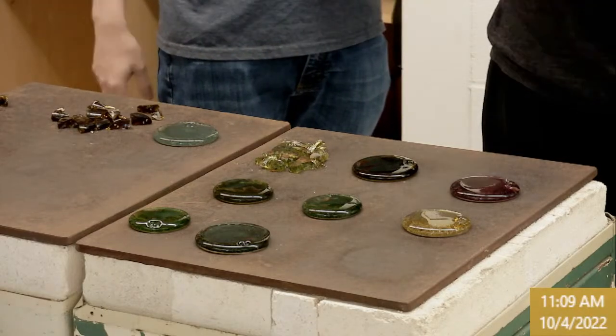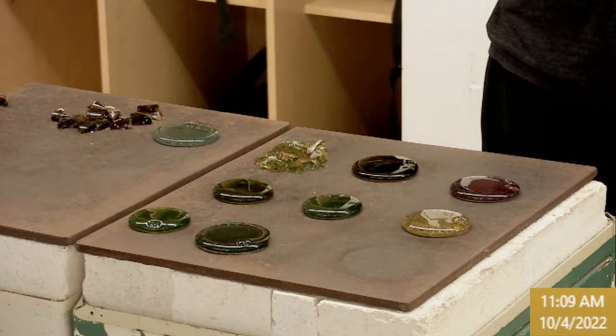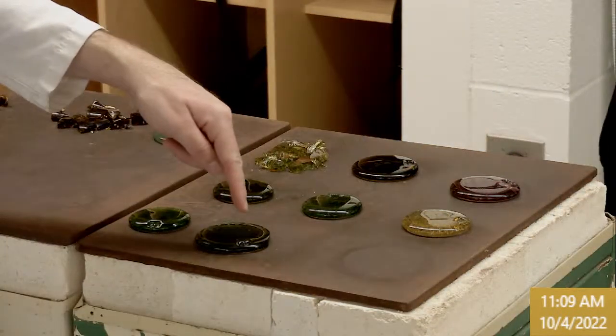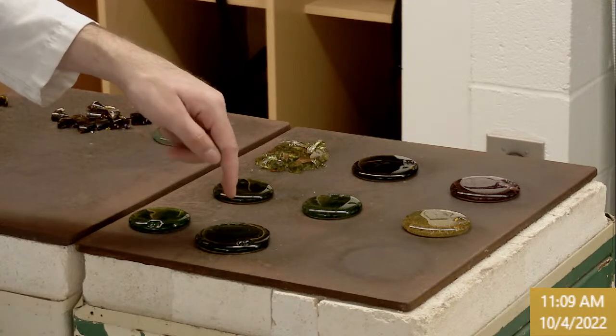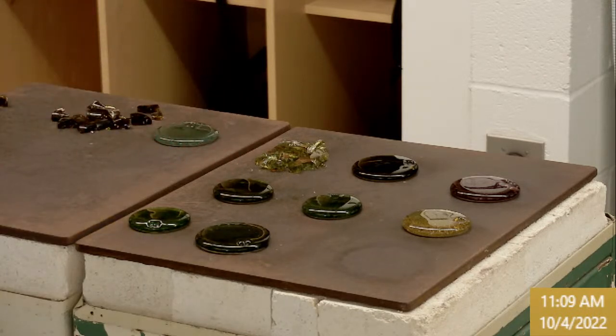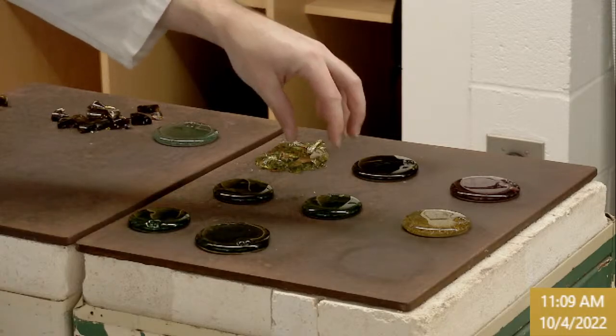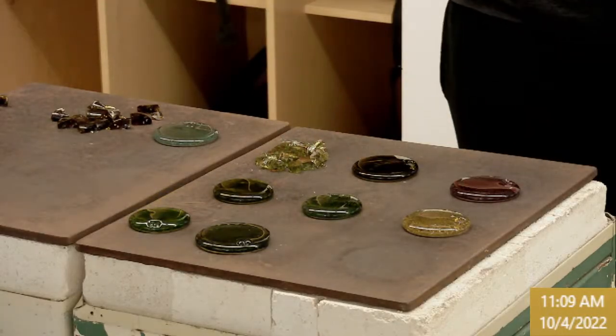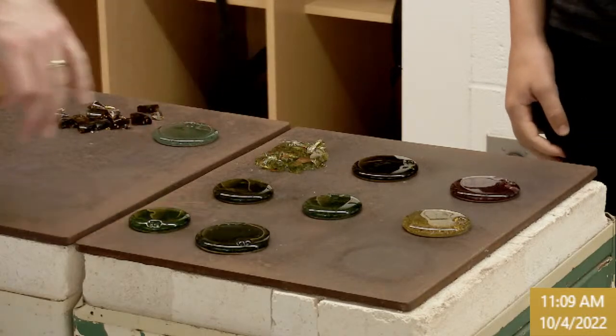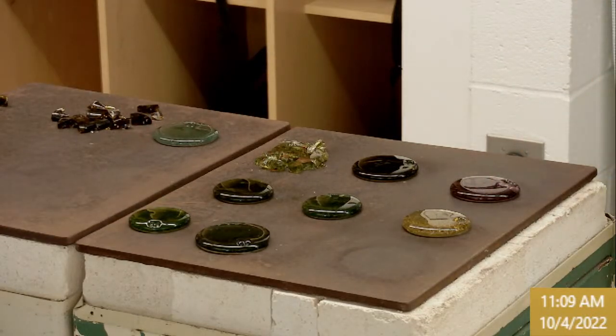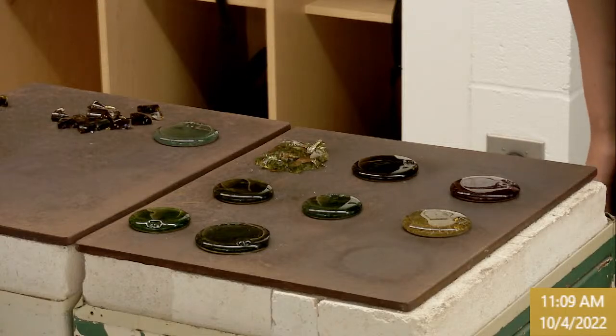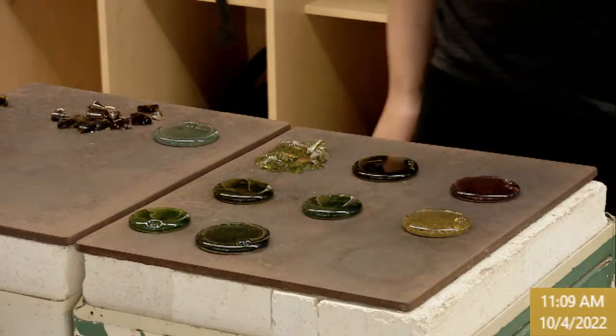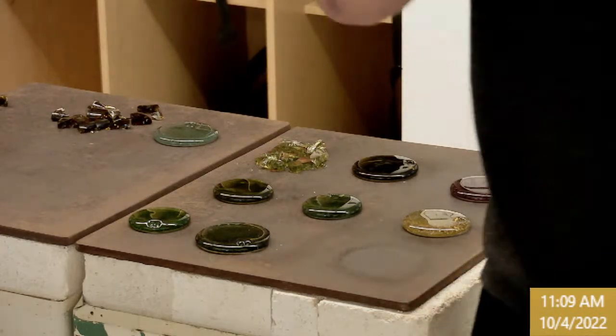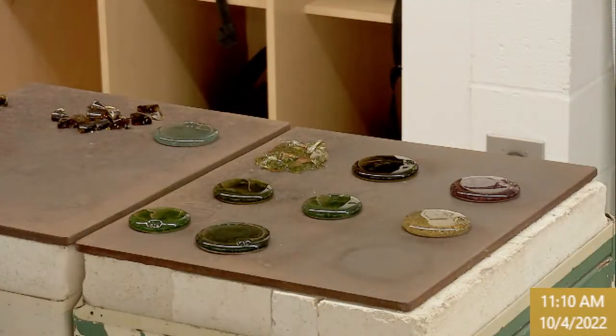High viscosity spreads less. Our lowest viscosity was probably this one that did a side shatter because it had the borate, so that one poured the easiest. The one with the smallest or tightest diameter was probably the highest viscosity. So we've got a couple of them. High viscosity spreads less. It's thick, so when it hits the surface, it stays in a taller stack and doesn't spread out as much. The lower viscosity spreads and flattens.